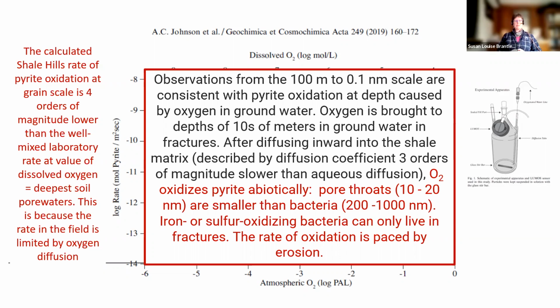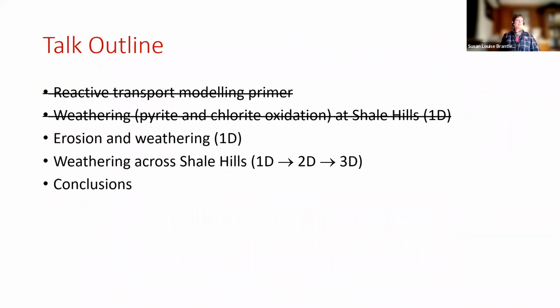I didn't emphasize this, but I told you that the pore throats in the shale are like 10 to 20 nanometers, and that is much smaller than bacteria. And so if there are iron or sulfur oxidizing bacteria in the system, and we think there are because we've worked and analyzed them, they can only be living in the fractures, and yet the oxidation is happening in the matrix. So the rate of oxidation is abiotic, and we think it's paced by the erosion. It is slow because of the erosion. It is actually dictated by how fast the clast moves up through the system.